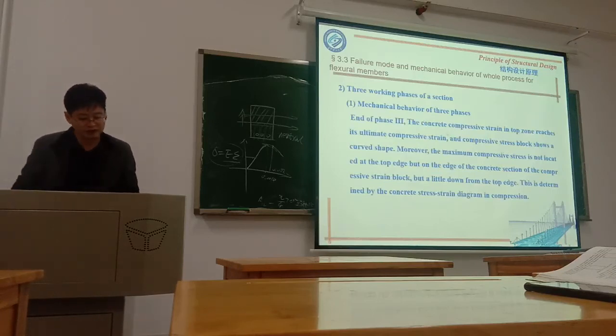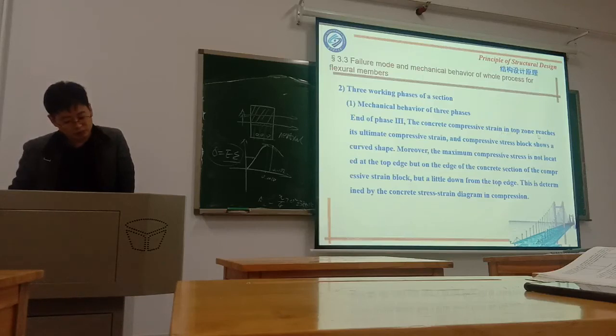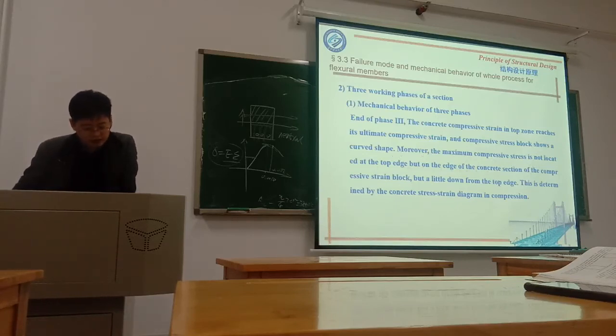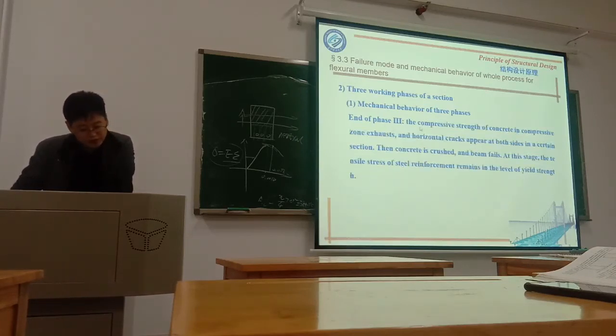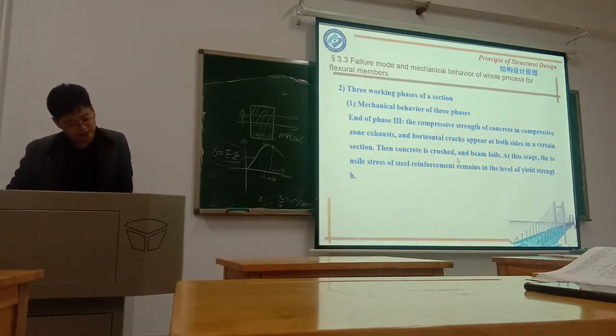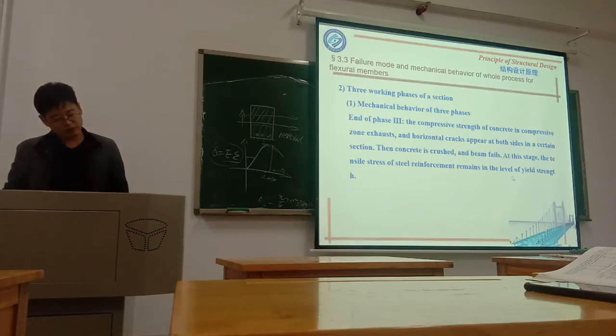At the end of phase 3, the concrete compressive strain in the top zone reaches its ultimate compression strain, and the compressive stress block shows a curve shape. The maximum compressive stress is not located at the top edge, but a little down from the top edge. This is determined by the stress-strain diagram. So at the end of phase 3, the compression capacity of the concrete in the compression zone is exhausted, and horizontal cracks appear at both sides in a certain section. Then the concrete crushes and the beam fails. At this stage, the tensile steel also reaches yield strength.